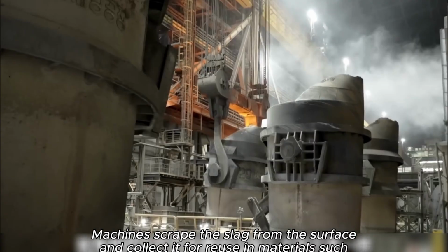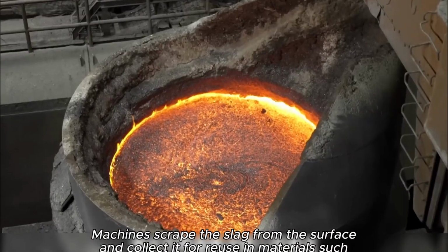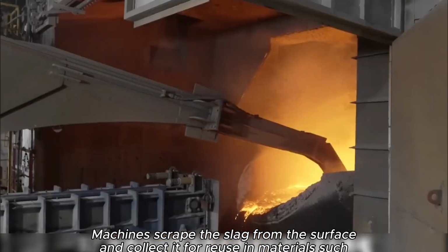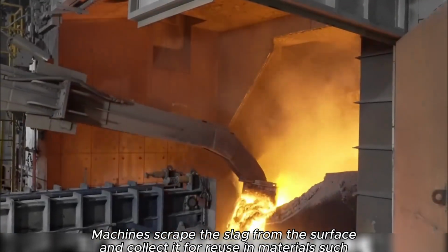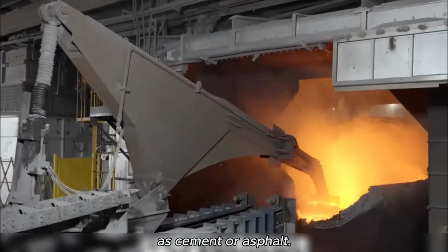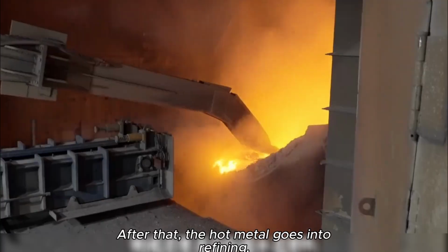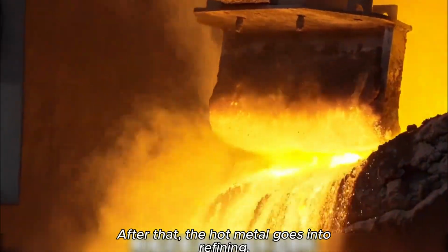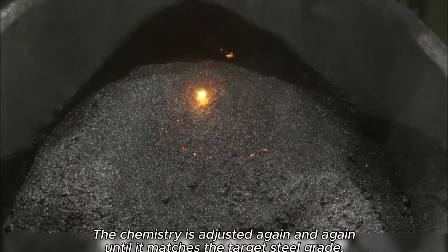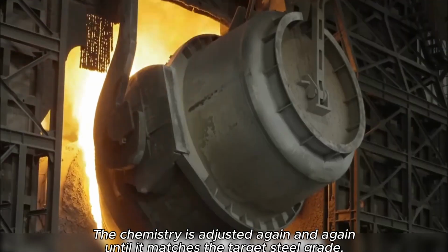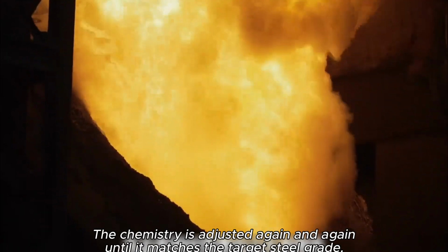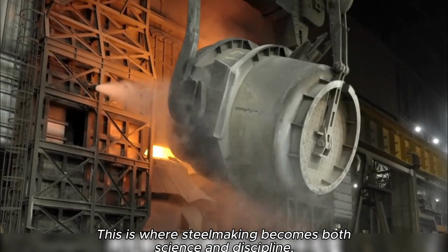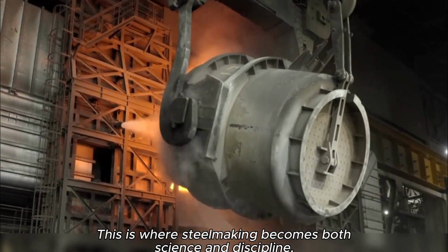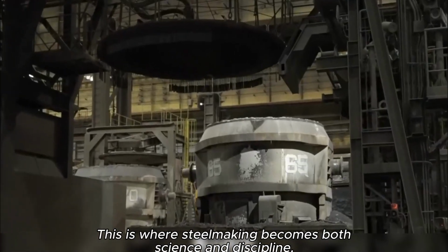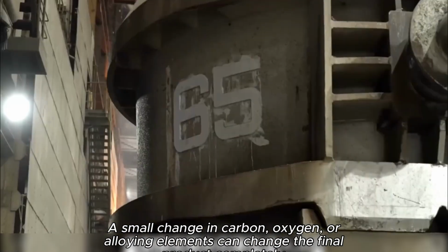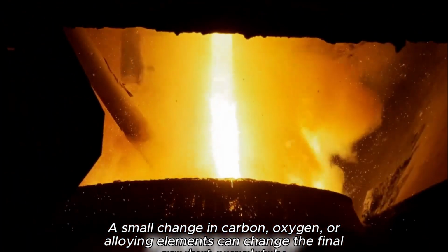Machines scrape the slag from the surface and collect it for reuse in materials such as cement or asphalt. After that, the hot metal goes into refining. The chemistry is adjusted again and again until it matches the target steel grade. This is where steelmaking becomes both science and discipline. A small change in carbon, oxygen, or alloying elements can change the final product completely.